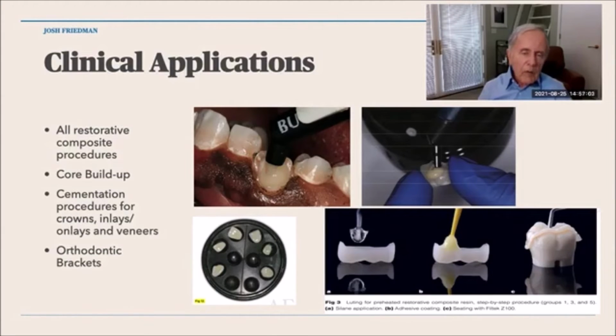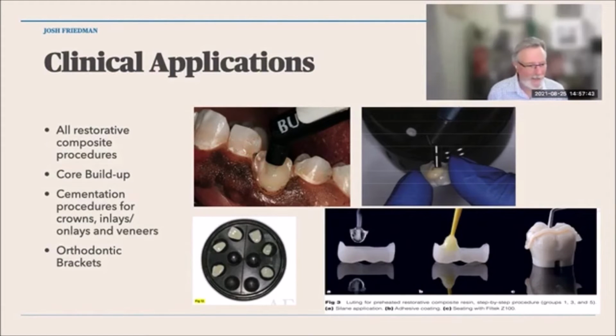If, for example, you're going to do a porcelain veneer, one technique is to warm the veneer with the composite in it and then place that on the tooth, of course, after you've prepared it and done those procedures. And what you find is that the material will extrude around the margins of the restoration and cool rather quickly when it's outside of the restoration, making it much, much easier to remove with an explorer. So in effect, you're getting a better bond, a stronger bond, and you're reducing the time it takes to do veneer bonding procedures. Yeah, I read several articles about that, and I was really impressed.